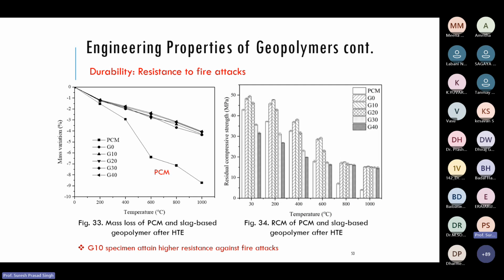Huge mass loss is there in the Portland cement, and the corresponding residual strength at 1000 degrees shows that the strength has reduced much, maybe from 45 MPa to around 5 MPa. That much loss of strength occurred once it was subjected to 1000 degrees centigrade heat exposure. But here it has retained almost 20 MPa. All the materials having glass content have retained strength, but geopolymer concrete, and particularly G10 and G20 having 10% and 20% glass powder, show the highest retention of strength under high temperature exposure. This is one of the better findings we got in comparison to our Portland cement.